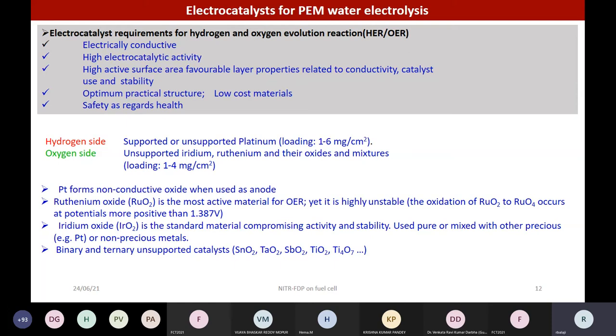And you cannot use a pure metal also, because when you do this kind of oxygen evolution reaction, the metal may have a tendency to react with oxygen and further form a metal oxide. So in order to avoid such complication, you use an electrically conductive noble metal oxide, especially iridium oxide and ruthenium oxide. These have good electrical conductivity, but at the same time good stability, because the metal is already oxidized in the form of plus 2 or plus 4. So it will not undergo further oxidation with the oxygen which is produced at the anode compartment. That's why it is preferred to use a metal oxide based electrocatalyst for the anode side, and it should not be supported by carbon also.